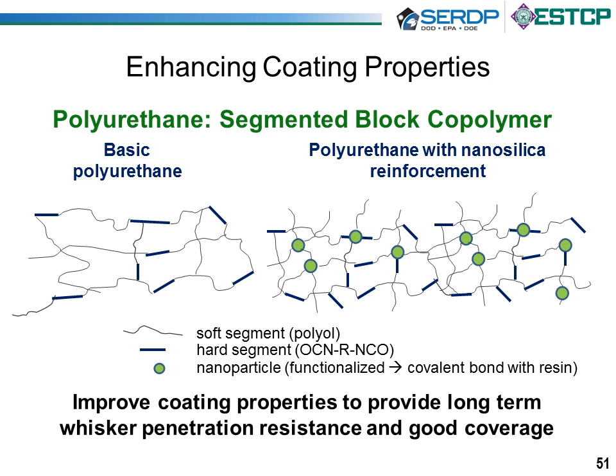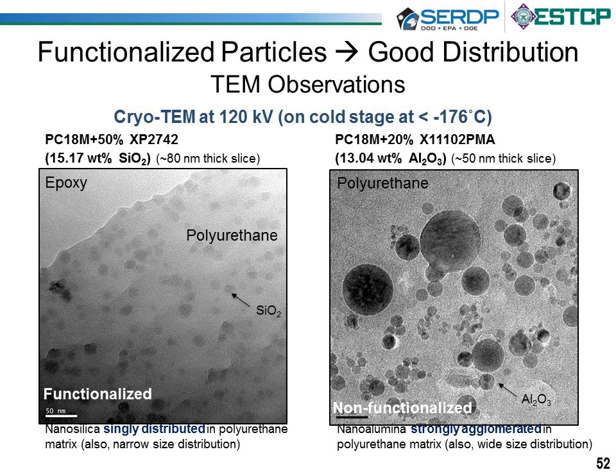The starting place we have is a segmented block polymer polyurethane. The basic thing is that there are some soft segments that provide stretchiness, some hard segments that provide stiffness, and we have added some nanoparticles. The key thing for us is we were looking for a nanoparticle that, instead of being a passive filler, functionalizes the surface so that it adheres well to the resin matrix, so we can get the biggest bang for our buck, so to speak. The particle is an active part of the overall system, so we can add less of it to get the desired improvement in mechanical properties, and we have also seen some improvements in coverage.